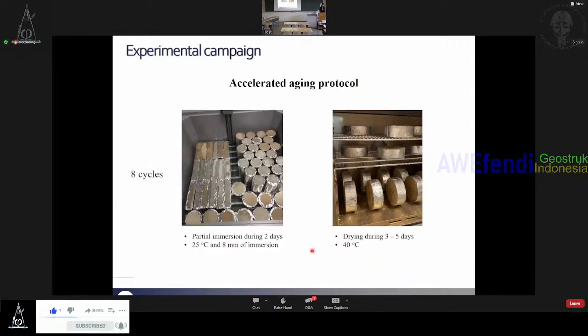After the concrete manufacturing, the samples were stored for 28 days before submitting them to the accelerated aging. The laboratory protocol is based on 8 successive cycles of partial immersion and then drying. The partial immersion was at room temperature, 25 degrees, and lasted 2 days. The samples were immersed at 8 millimeters. The drying part lasted 3 to 5 days, depending on whether it was a weekday or a weekend, in a ventilated oven at 40 degrees. For both the immersion and the drying, the sides of the samples were covered to ensure a unidirectional flow.